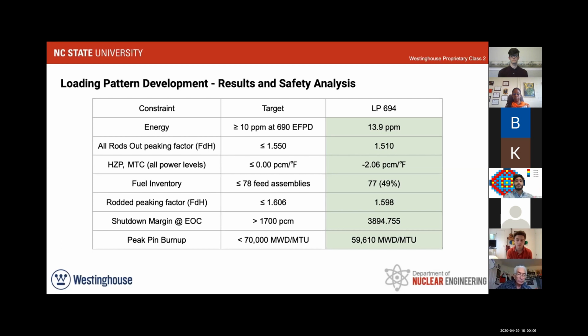For the peak burnup limit, we easily passed this limit. Even though our peak burnup limit was increased to 70,000 megawatt days per metric ton uranium to accommodate the highly enriched core, we can meet the peak pin burnup even with current industry standards at about 60,000 megawatt days per metric ton. So this was a very good outcome for the core that we designed.